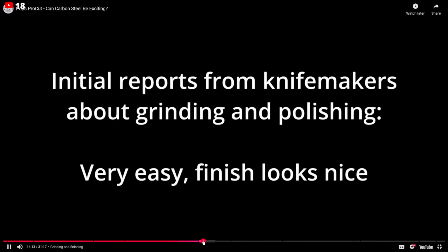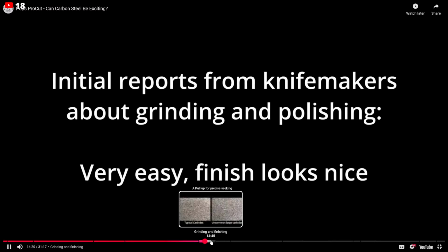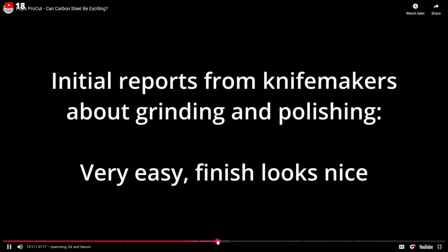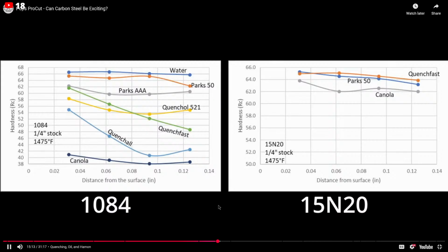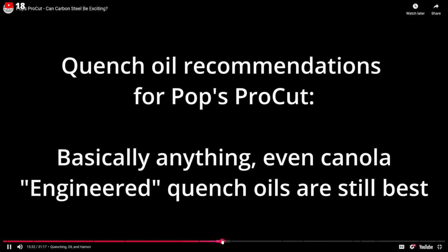Grinding and finishing, so far, grinding and polishing is very easy. So all signs are positive right now. I haven't seen any mirror polished blades. Maybe those would be more difficult, but for quenching oil, that is pretty high. I also found this in testing 15N20. So that high nickel, any quenching oil, even canola, works with relatively thick cross sections.